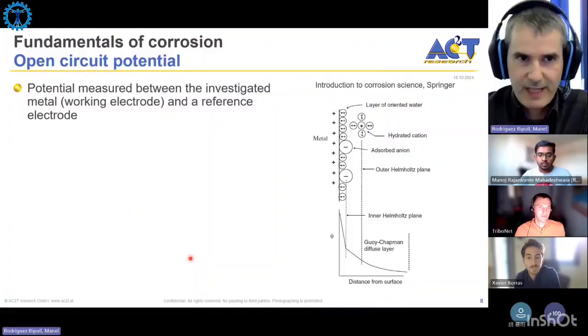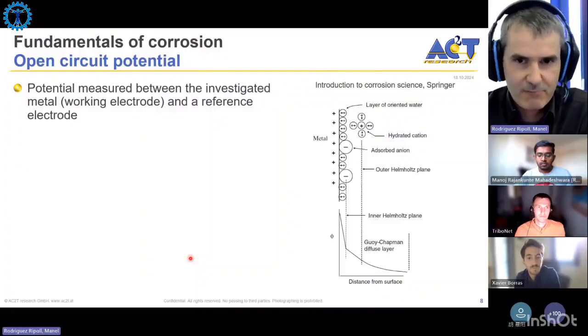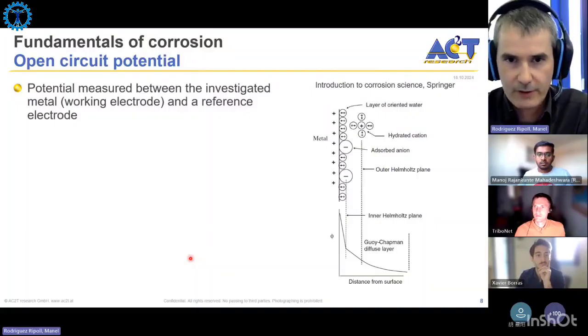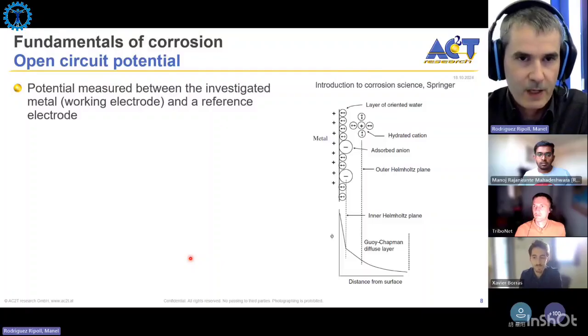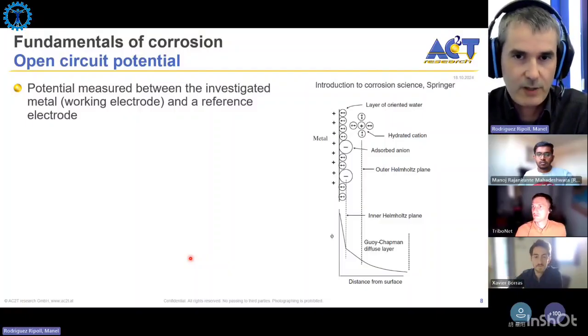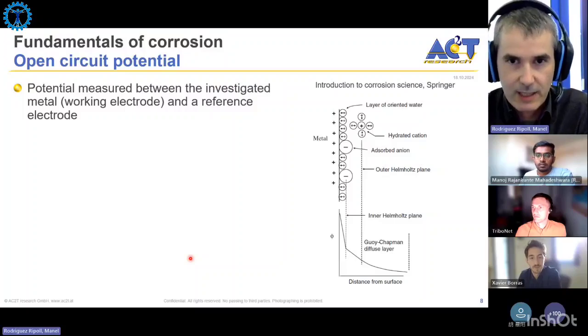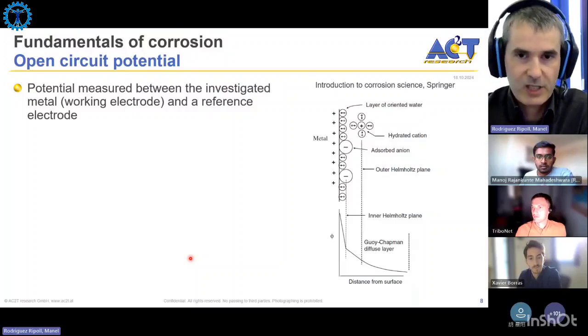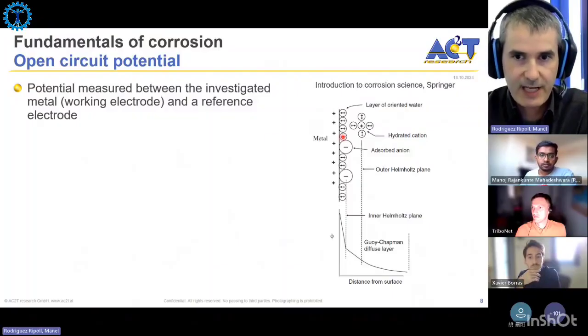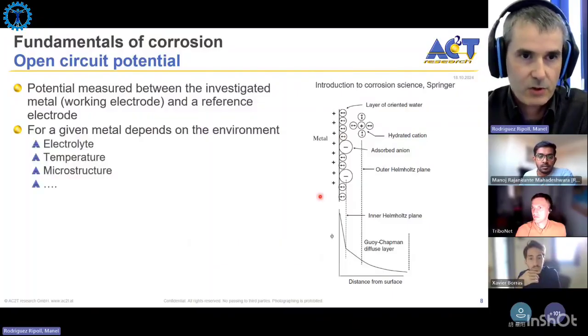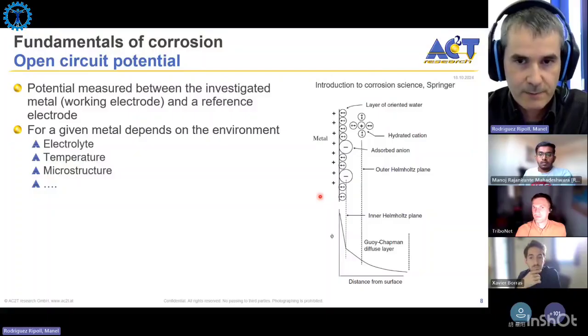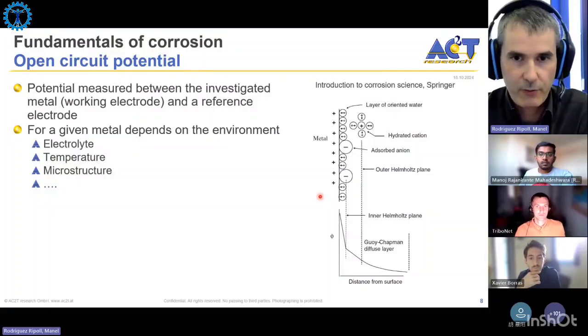Without entering into too many details, we can already have a certain feeling that when we have an electrolyte with dissolved ions like sodium chloride or protons from an acid, or we have water, which is also a dipole molecule that can get oriented, we already see that during metal dissolution we emit electrons. At some point we will reach an equilibrium with these electrical charges, and we will end up creating a potential. This potential that we create in equilibrium is what we call the open circuit potential, the corrosion potential, that is spontaneously occurring when we immerse a metal into an electrolyte.